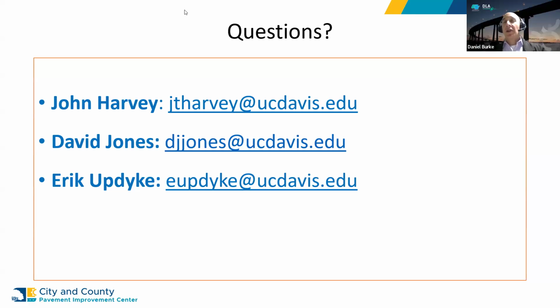Excellent. And just another comment here is that cold recycling also works well as a base course for widening the road and placing an overlay over the whole road. Do you agree with that? Yes, absolutely. We certainly have seen that on very narrow roads. So if you've got an unbound shoulder, just your native materials, you can mill that out as a separate exercise. You probably don't want to include that in your pavement if it's very marginal materials, has high clay content, or doesn't have a good gradation. But you can actually mill it out and turn it into a bit of a box cut there.